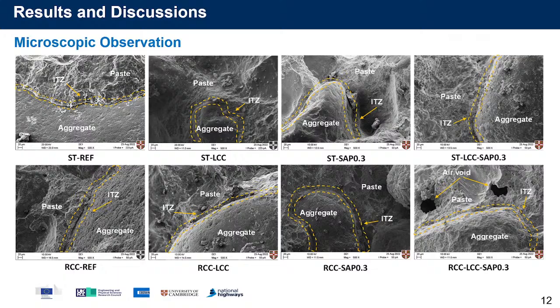And finally, this slide shows some microscopic observations. It shows the positive impact of using GGBS in improving the interfacial transition zones of the aggregate, and the bonding between the cement and aggregate. In the bottom right-hand side images, you can see that with the inclusion of superabsorbent polymer, we have some air voids that negatively impacted the compressive strength and some other performances.